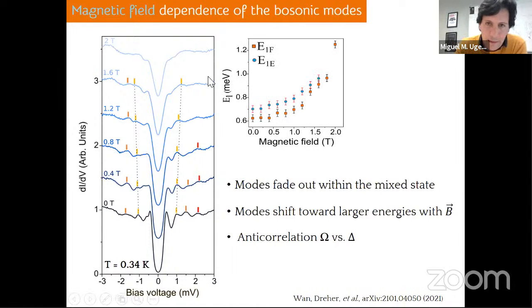Right here, I show you how the fundamental mode is behaving with the magnetic field. If you follow this fundamental mode, you can see that apart from becoming weaker and weaker, these resonances separate from the Fermi level as we increase the magnetic field, in a nonlinear way. So this is for the fundamental mode for the empty states, and this one is for the filled states, and they behave in a similar way. But this is the energy with respect to the Fermi level.